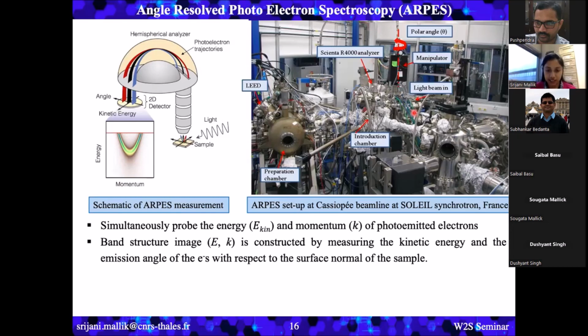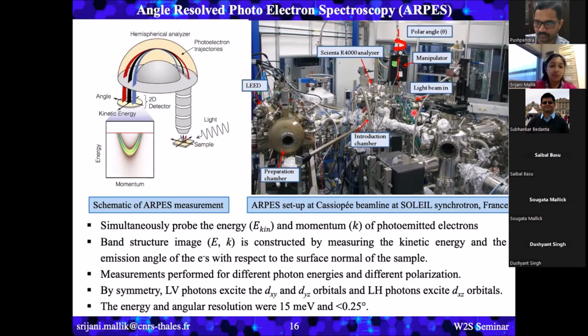We did measurements for different photon energies as well as different polarizations, because by symmetry, LV photons excite the dXY and dYZ orbitals, and LH photons excite the dXZ orbitals. To have a full overview of all the orbitals present in the band structure of KTO, we tried different polarizations. The energy and angular resolutions were 15 meV and less than 0.25 degrees.